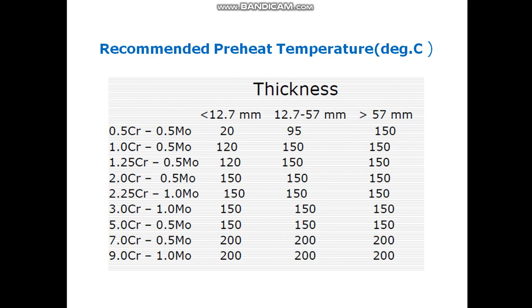This table provides some guidelines and recommendations on the preheat temperature in degrees Celsius, for compositions from half chrome half moly to 9 chrome 1 moly, for thickness ranges of less than 12.7 mm, between 12.7 to 57 mm, and greater than 57 mm. The recommended preheat temperatures are tabulated here. As you could see, when the composition becomes richer in chrome moly, for the higher thicknesses, the preheat temperature is minimum 150 degrees Celsius. And for 9 chrome 1 moly steel and 7 chrome half moly steel, the preheat temperature is 200.